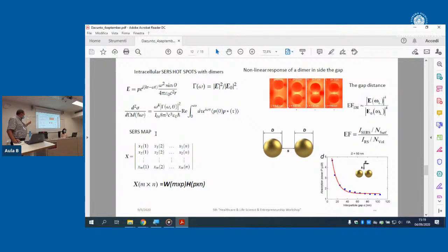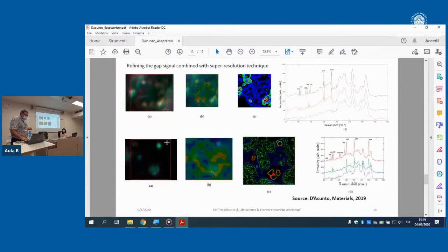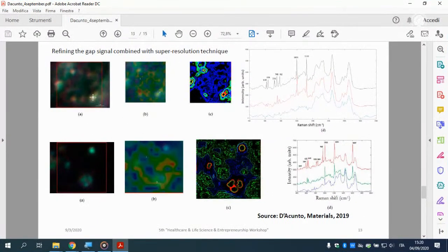It's different from the Raman map, because we enhance only the SERS signal in our system. So now we have 3 different images. This is inside the cell with dark field. This is the Raman map. This is the SERS map. The red is where we are taking signal only in this region. And only in this region, we have 3 different signals.